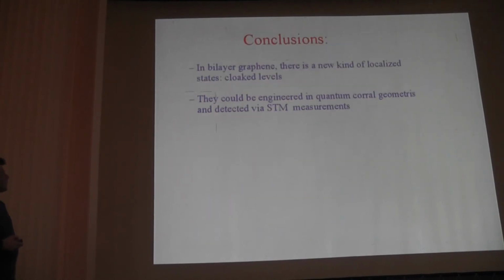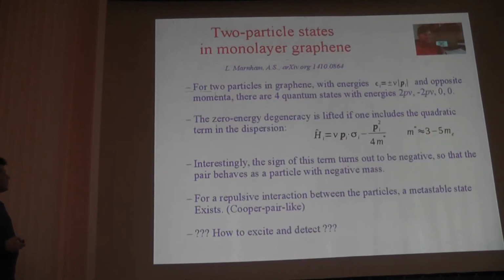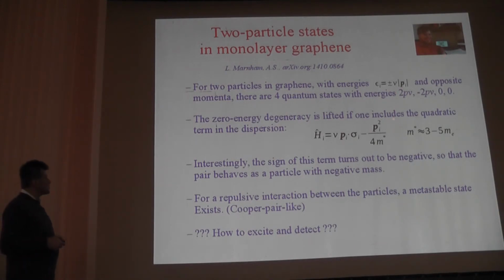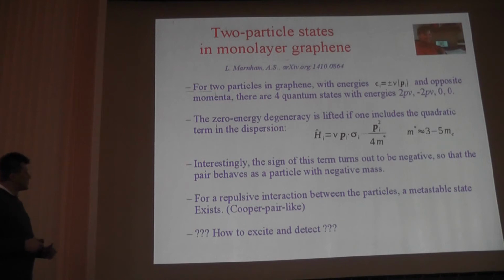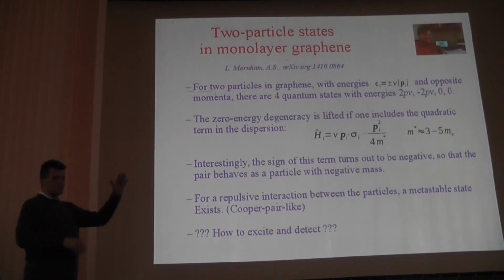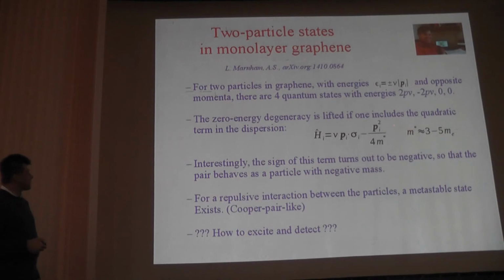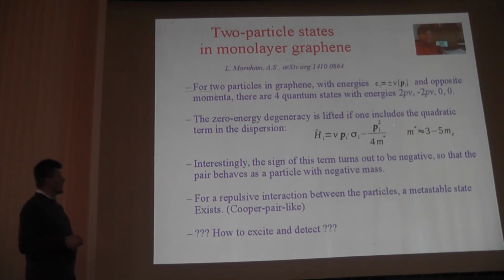So one of my PhD students was recently involved in a different kind of project involving localized states. Those were the states in single layer graphene formed by two quasiparticles in two opposite cones. The kinetic energies from the two cones would cancel, so one should look at small deviations from the cone structure. And the result was that a pair of electrons in opposite cones in graphene behaves as a particle with negative mass.